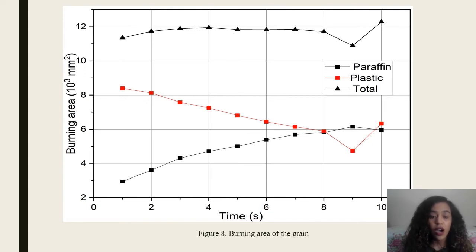According to the regression rate equation 1, it opens the paraffin surface to the hot-reacting flow. At the same time, the protection layer of plastic resists the thermal loads protecting the fuel from overheating. The regression rate of protective material was estimated from 0.25 to 0.49 mm per second and paraffin from 1.14 to 1.38 mm per second. The most significant regression of the protective layer happens in the port of the grain, where the cross-sectional area is minimal and the flow velocity is maximal. Such behavior was also observed previously by other authors.